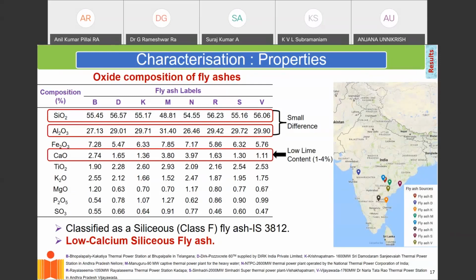The other thing is there is very low lime content in our fly ashes. It basically contains very little calcium oxide. So this is a unique characteristic of most Indian fly ashes, where they're very low in lime content. The silica and the alumina contents by themselves are not indicative of the true reactive potential of these fly ashes. And reactive potential is important because when I'm looking at replacing cement, which is a very reactive material, I need to see how much of cement I can replace with fly ash. So therefore, I need to assess its true reactive potential. And unfortunately, just looking at oxides, we are not able to infer the reactivity.